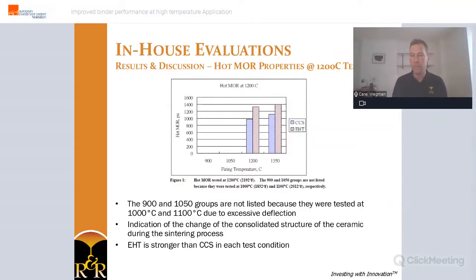When the firing temperature increases, the hot deformation of the shell decreases. It becomes stiffer. And it indicates a change of the ceramic structure during this sintering process. At a lower firing temperature, the strengthening takes place mainly through a rearrangement of the silica particles in the binder. At a higher firing temperature, a glass phase sintering mechanism begins and further strengthens the structure of the entire ceramic sample. So therefore, when fired to higher temperatures, the glass or liquid phase will eventually form a more profound network that holds the refractory grains and provides further strength.